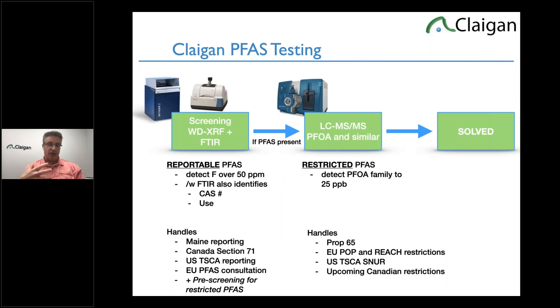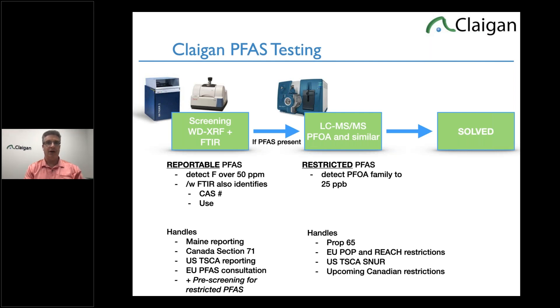When we're doing PFAS testing — and I'm going to talk about what PFAS we're seeing — there are two pieces. The main one for all this reporting is a screening using the WDXRF. A lot of people ask for a list of CAS numbers for PFAS, but it's not about that. It's literally what you're using — it's a polymer. It's just whether or not the fluorine is over 50 ppm. No fluorine, no perfluoroalkyl substance, no PFAS. It's that easy.